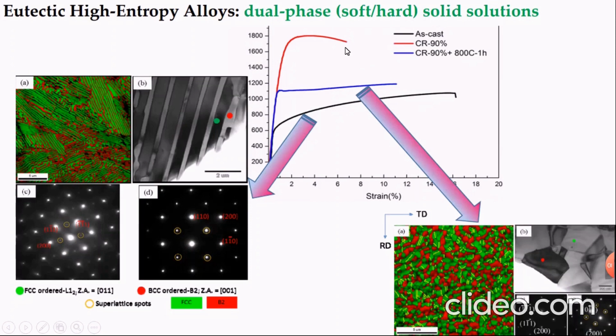Here also we can see that in high entropy alloys, similar to the conventional alloys, we can increase the properties by cold rolling, which is very good if we need to acquire higher strength. Of course, in high entropy alloys, it's better to study the microstructure by transmission electron microscope, because most of the features that give the properties to the high entropy alloys cannot be seen without it. So it's very important, especially if you design a new alloy and you need to reveal the reasons behind the good properties, you have to use transmission electron microscope facility.